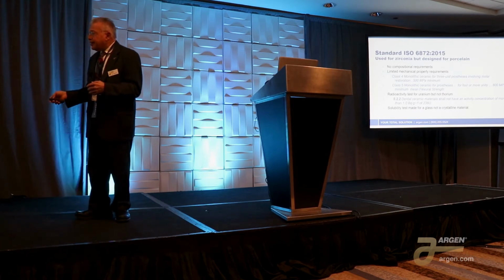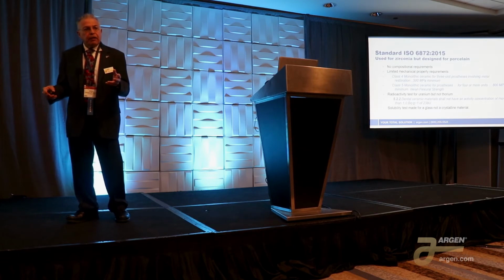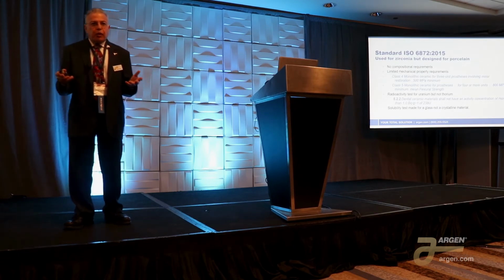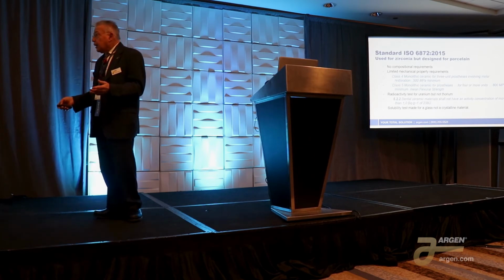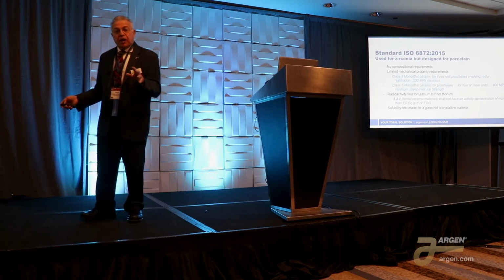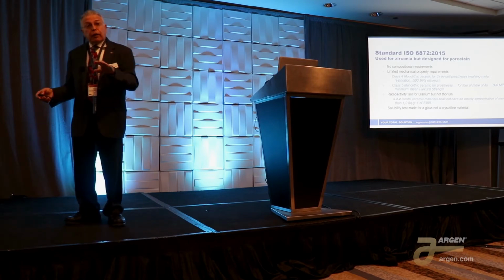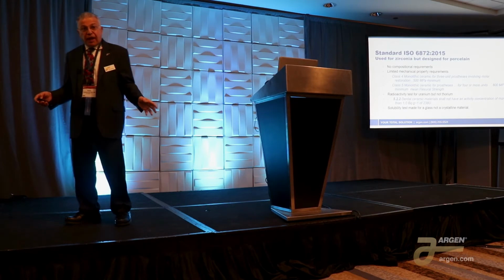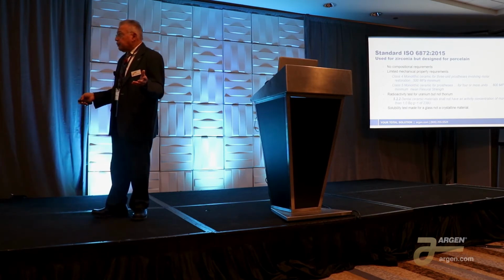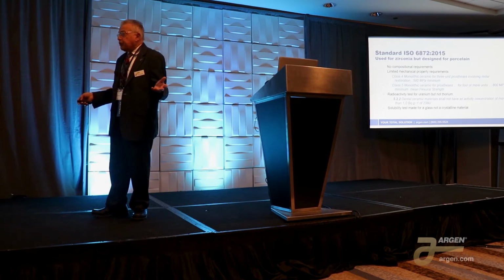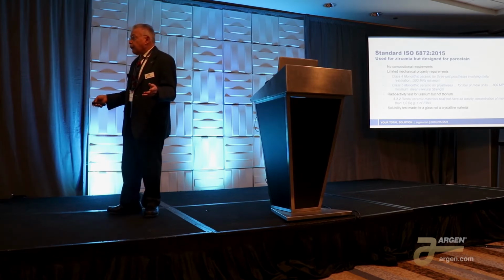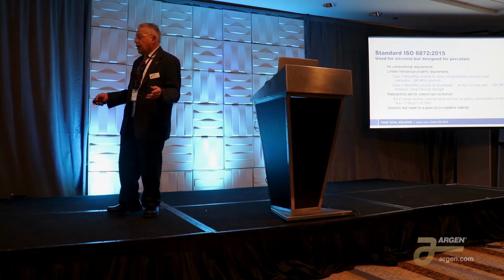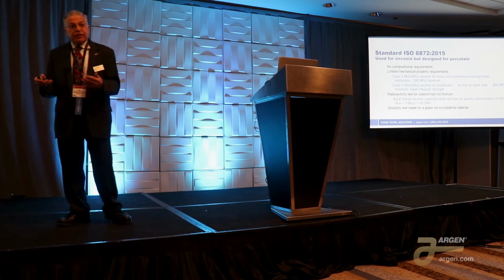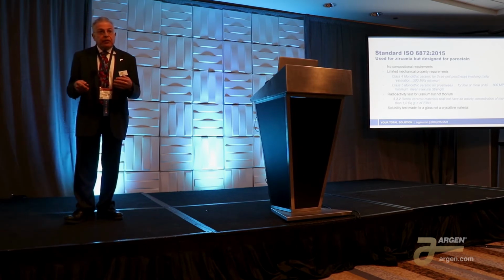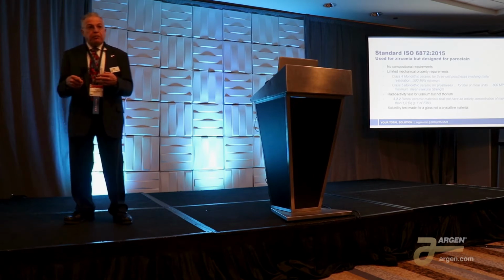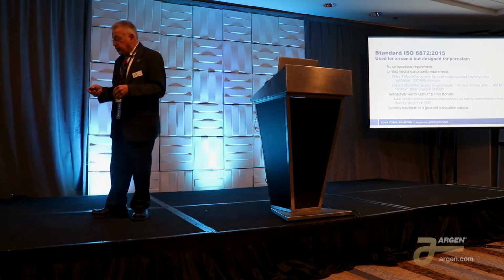So what happens is this standard has no compositional requirements. The manufacturer is under no obligation to tell you what's in that zirconia. It has limited mechanical property requirements, because the mechanical property requirements were developed for the aluminous porcelain back in the 1960s. And that were, number one, for a 3-unit prosthesis involving a molar, that the flexural strength has to be at least 500 megapascals. Or for 4 or more units, 800 megapascals. Well, you may have experienced that that doesn't work for zirconia. The material has to be a lot stronger than 800 megapascals in order to make more than 4 units, especially when you have 2 pontics next to each other.